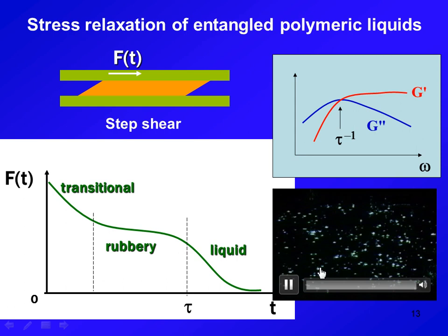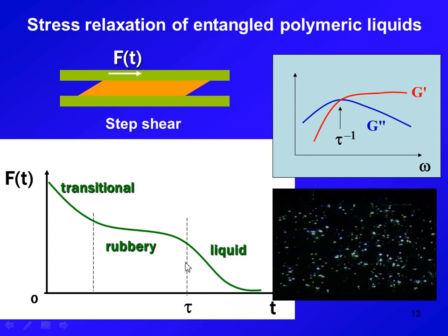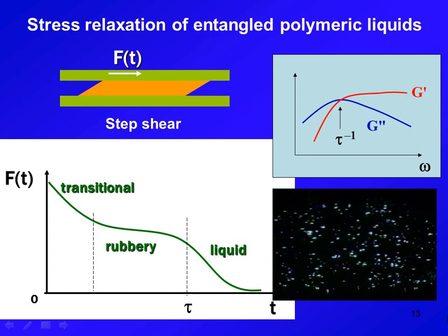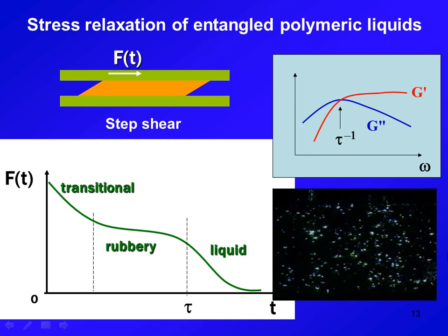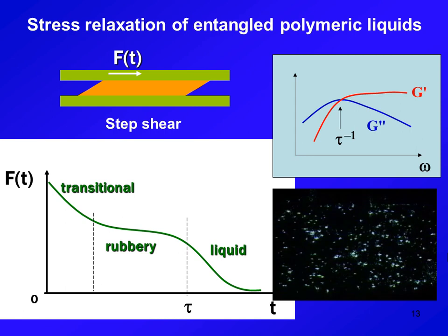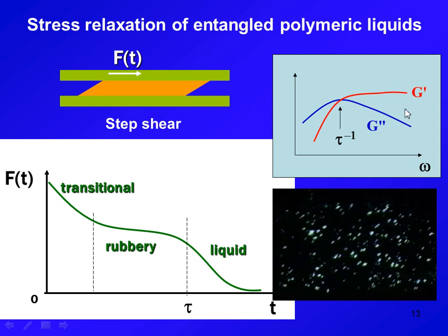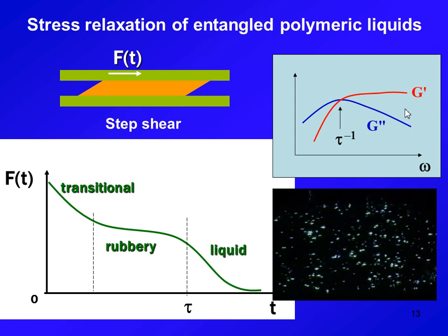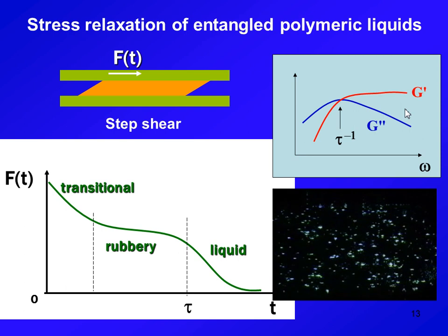And this can all be obtained, particularly the information about that relaxation time, by performing so-called oscillatory shear, or small amplitude oscillatory shear. This movie shows a peek into that gap of 1 millimeter. As I sweep the frequency, what happens when I measure the force? Then I find, in agreement with Maxwell, that the response is elastic-like when my frequency is very high relative to the relaxation time.